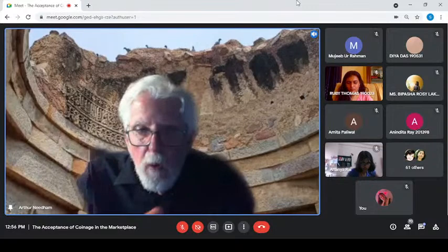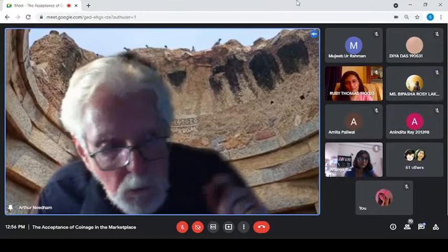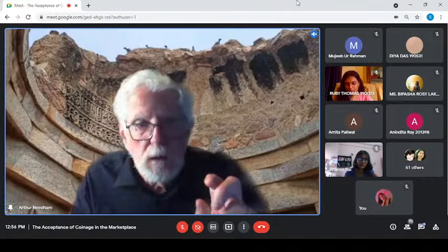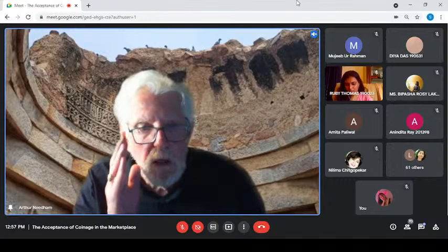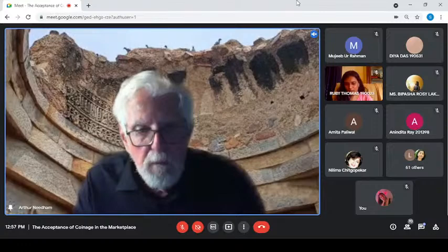And I'll tell you a silly thing that we found in the Ashmolean tests. Everyone ran and said, look, there's a coin called the Bombay tin piece. And I'd always said, no, it's not always made of tin, it's made of zinc. So we tested it, and certainly from a specific date, it was made of zinc. And I said, well, the zinc came from India. Of course, they had the best zinc smelting in the world. Now they're saying the zinc came from China.